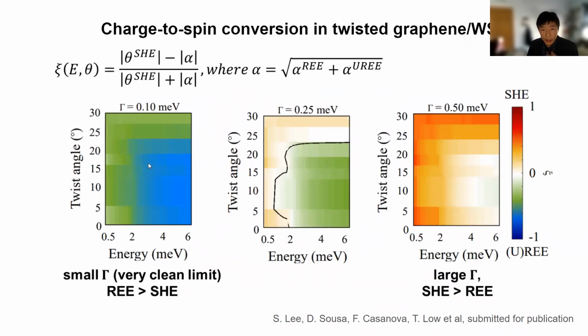So in summary, we look at the spin Hall effect and the Rashba Edelstein effect in these graphene and TMD twisted materials. Here, what we are studying is how disorder, the broadening, matters. In this case, we use a very crude way of modeling the disorder just by adding a broadening term. Of course, this is not accurate, because if you do it in this manner, it doesn't preserve the net current that's coming into what we call these disorder probes. But in any case, it gives us a rough idea of what is happening when we have disorder.